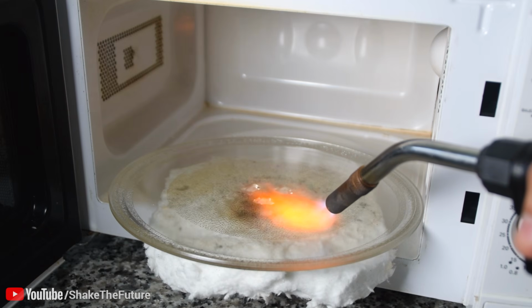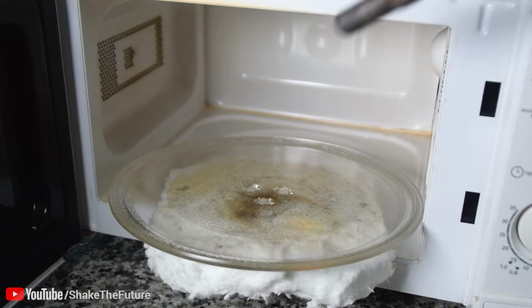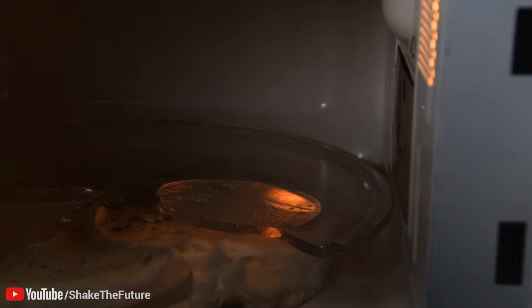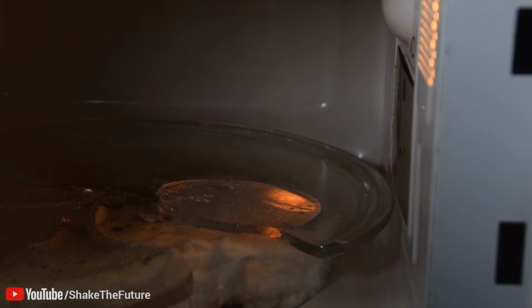Turns out the glass plate was hot from previous use. Because it's hot, now it will start to absorb more microwaves. The more microwaves it absorbs, the hotter it gets. The hotter it gets, the more microwaves it absorbs. Here's a quick demonstration. If you heat up the plate in one spot with a blowtorch, it will keep heating up in the microwave. It's good that I didn't need it.